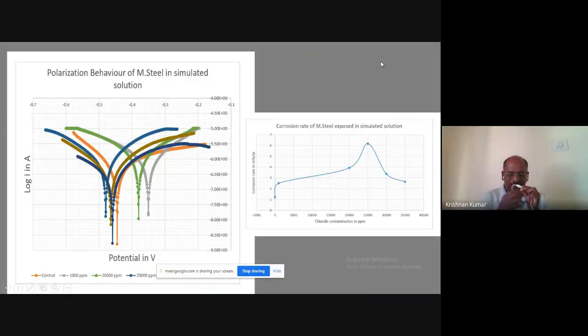And in our laboratory, we have done some studies. What is the effect of chloride on steel reinforcement? This is called polarization measurement. For the steel reinforcement, we used a three-electrode system in the laboratory cell. There we made the polarization from cathodic to anodic. You are seeing that there are different chloride levels.